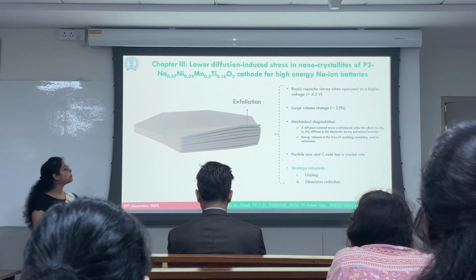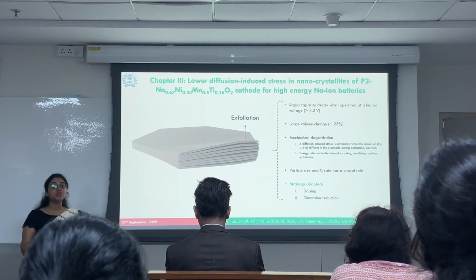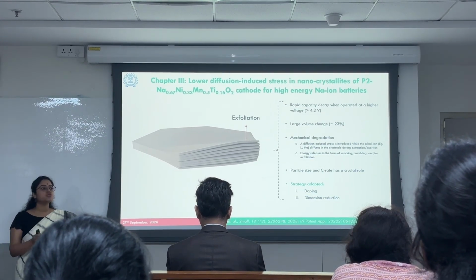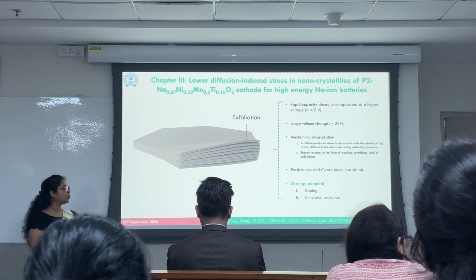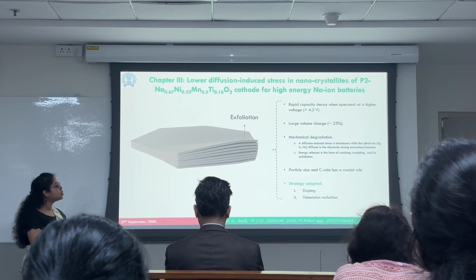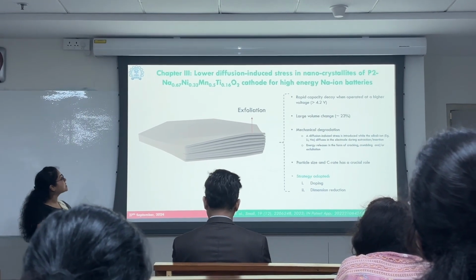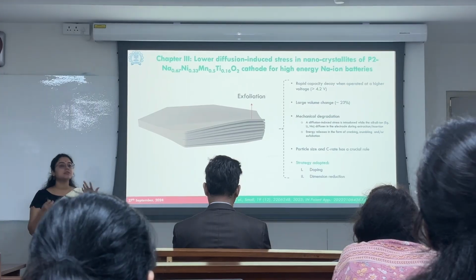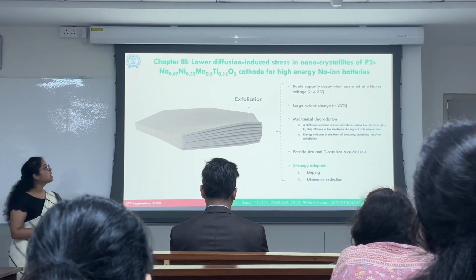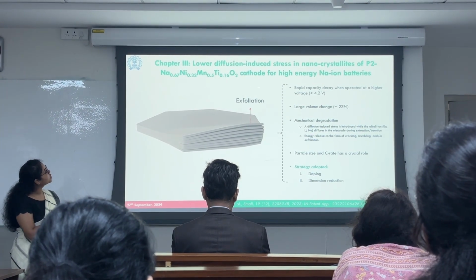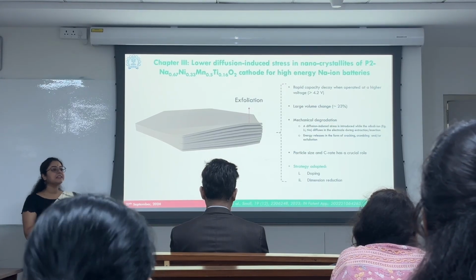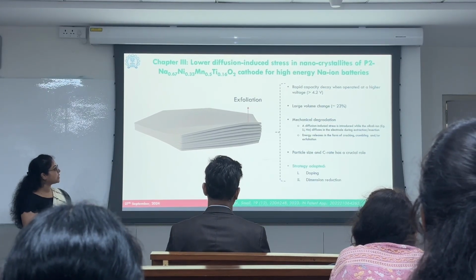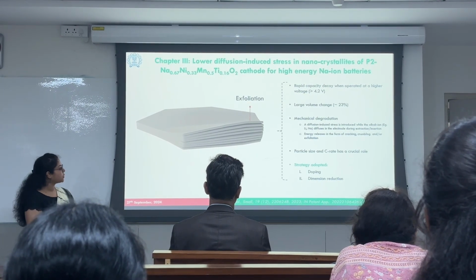Hence, we understood that particle size and C rate have a crucial role to play in order to make mechanically robust cathode materials. So we adopted the strategy of doping. In this case, we doped titanium and followed the strategy of dimension reduction. So we have abbreviated this particular cathode material as NMTNO, and the nano has been derived as NMTNO nano, and the micron as NMTNO micron.